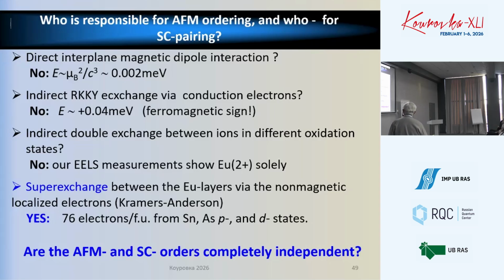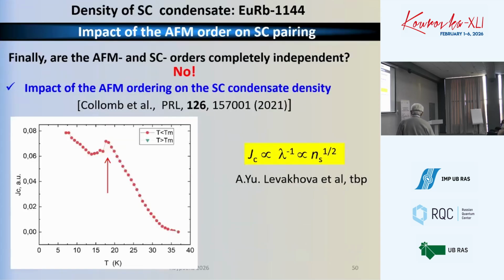Now, since we decouple antiferromagnetic ordering and superconducting pairing, are they indeed completely independent? It seems to be so, but in fact not. The antiferromagnetic ordering does not affect the superconducting order parameter, but it does affect the density of the condensate. It can be measured by either Hc1 with the magnetization probe, or from the critical current, which is one over penetration depth, and also depends on the density of the superconducting condensate. And it shows some features at the temperature of magnetic ordering.